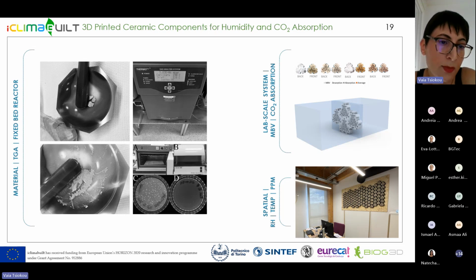So the CO2 absorptive properties of the crushed material have been tested using a thermogravimetric analysis and fixed bed reactor in collaboration with SINTEF. Whereas another aspect of utmost importance for our case has also been tested, which is the antimicrobial properties of these components, which are basically exposed to humidity. So we had to confirm that no bacteria would grow on these components, which has been confirmed with the respective test undertaken by our partner NTUA.